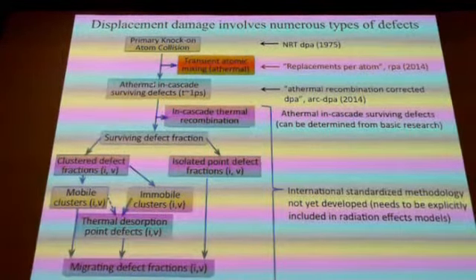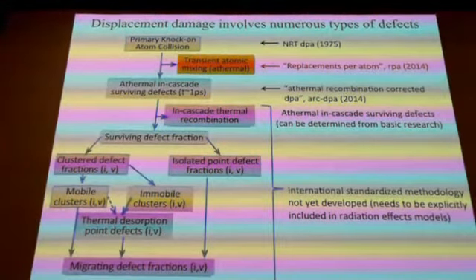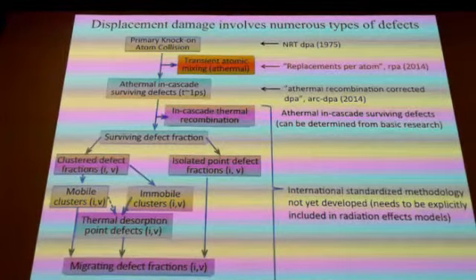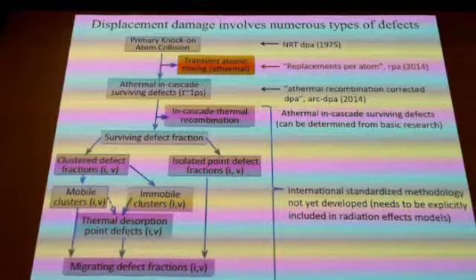But again, what it didn't do was look at the transient atomic mixing that occurs within energetic displacement cascades and some of the recombination of the defects that leaves you with a net reduced fraction of defects compared to what's actually being produced according to the NRT DPA model.